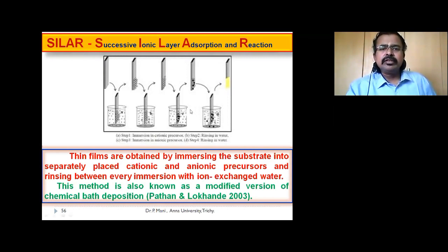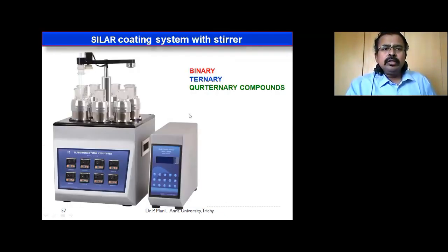Here we are seeing 4 different beakers, and the first one is immersion in cationic precursor, and the third one is anionic precursor, and these two, B and D, are deionized water, right? This is the setup, and there are 3 different setups: for binary, for ternary, for quaternary compounds. This setup is for quaternary compounds.